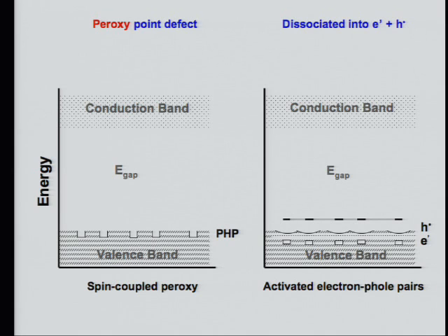But if some of the oxygens in this material exist there as pairs and have changed their valence, they represent a point defect which would make a little depression at the upper edge of the valence band as a peroxy hole pair, and the moment they dissociate and form these hole pairs, these defect electrons, then their wave function delocalizes and you actually get conductivity at the upper edge of the valence band.